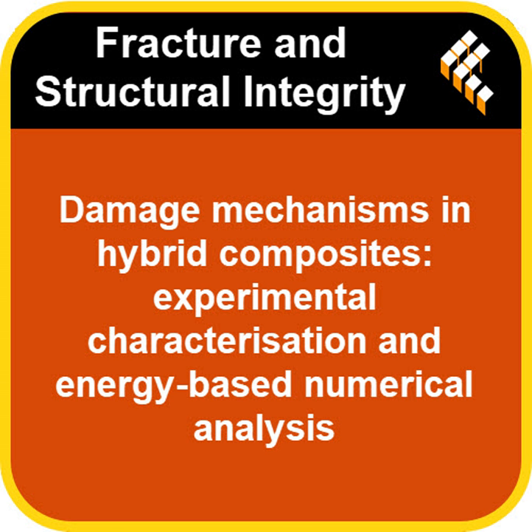What about the 6C2G? In the 6C2G setup, which has glass on the compression side, the initial tensile damage was in the very last carbon layer, or layer #8. Then it moved down to the fifth layer, #5. But the overall failure seemed more intense, more concentrated maybe. Why the difference? They think this is because carbon fiber is actually better at absorbing tensile damage energy compared to glass. Okay. What about the damage from squishing forces, the compressive damage in those two configurations?